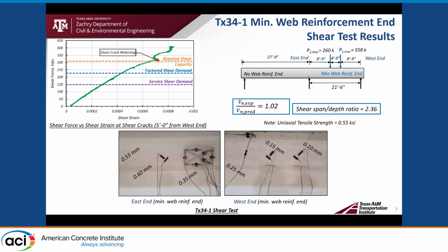Then we wanted to check the shear capacity of the minimum web reinforced end of the first specimen, and we conducted shear tests with span by depth ratio of 2.36 for all, and higher than 2 for almost all of the shear tests. You can see the shear cracks that were developed at that shorter span that we tested, and we had narrow cracks at the west end, and then we had wider cracking at the east end because this end was already more damaged due to the previous flexure test.